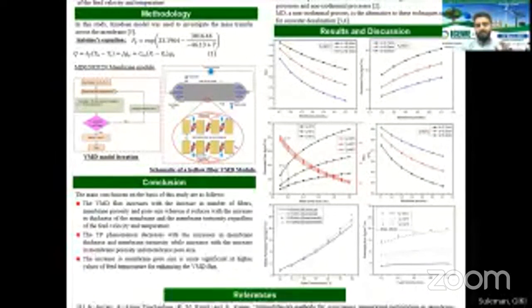The other thing is that the temperature polarization phenomena decreases with the increase in membrane thickness and membrane tortuosity, while it increases with the increase in membrane porosity and membrane pore size. Lastly, we concluded that the increase in membrane pore size is more significant at higher values of feed temperature for enhancing the VMD flux. Thank you.